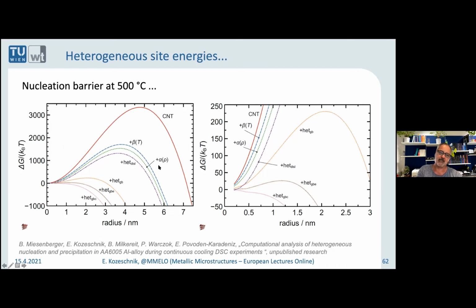If you add the size effect, it will not help very much because the particle is too large here. It's still a critical radius of 4 or 5 nanometers. The heterogeneous site energy of the dislocation could help a little bit, but not too much. But if you look at the grain boundary edge and grain boundary corner effects, then you realize that these heterogeneous sites can decrease the energy so much that nucleation will be possible now, also at the very high temperature, in accordance with experiment.